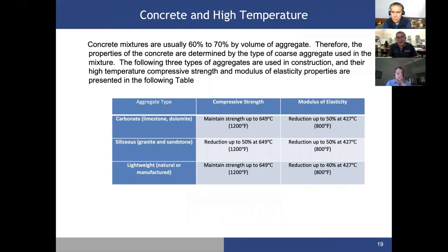Then the question becomes the concrete. The aggregate composition is very important on acceptable risk acceptance of the concrete. If there is carbonate, reduction up to 50% at 427 degrees. It means that if you know the temperature, you know that your modulus of elasticity has changed. Silicates, reduction up to 50% at 427 degrees, which is equivalent to 800. Lightweight, natural or manufactured, reduction up to 40% at 427 degrees C.